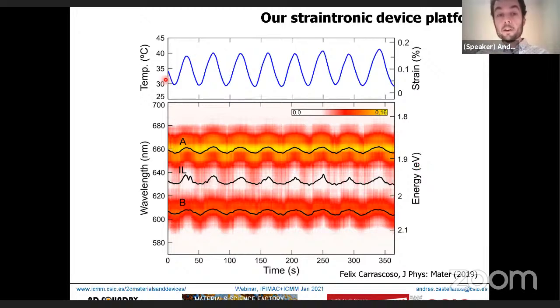What's important is that this technique allows us to quite easily change strain in time. For instance, in this case we took a heater and sent it a sine wave signal - here's the temperature of our heater changing in time. And here's the energy of the A, interlayer, and B excitons in time, following the same signal from the heater. Basically, we can modulate the band structure of our material in time, which is an interesting path toward fabricating a device that works with this strain.